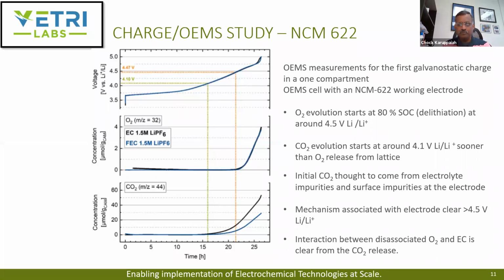Then that lined up everything. Yeah, it's quite possible that even without impurity, that you have some CO2 formation before substantial O2 evolution. Correct, exactly. And because that will create a local mass transport issue, and then the actual polarization of the cathode will be to a higher voltage. Exactly, and that will cascade.